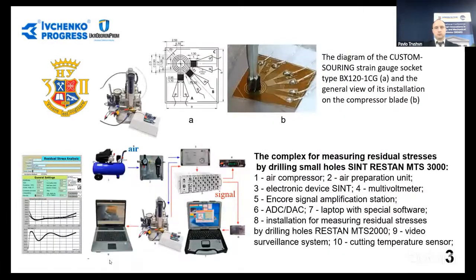The investigation of residual stresses in the surface layer of the blade airfoils was carried out using the method of drilling small holes, in accordance with the standard of the American Society for Testing and Materials, ASTM E837. The measurements were performed using the SINT RESTAN MTS 3000 system from Italy, which was a part of the integrated residual stress measurement system. The use of the drilling small holes method allowed us to determine the stress distribution in the surface layer at various points on both the pressure and suction sides of the compressor blade airfoils, sizes of which didn't exceed 20 by 20 mm, widely used in the design of small-sized gas turbine engines. High-frequency drilling modes were used, allowing the influence of the drilling process on the measurement results to be neglected.